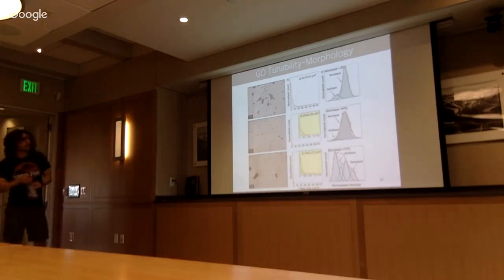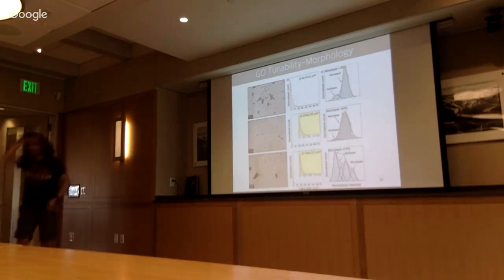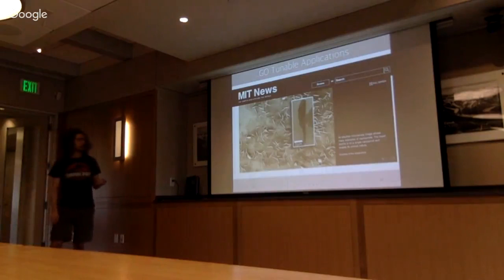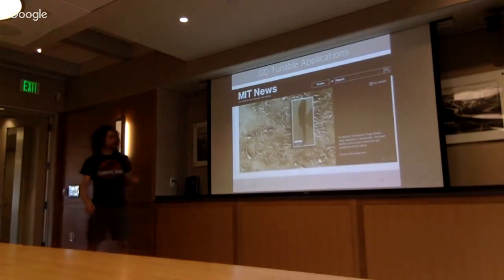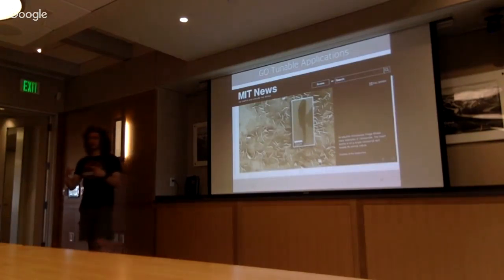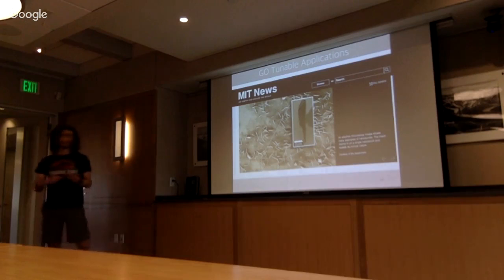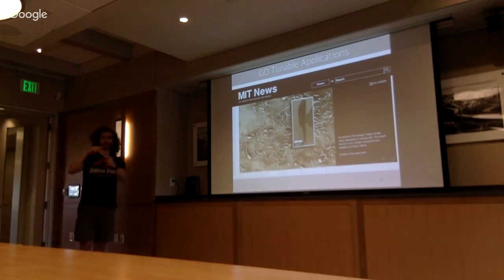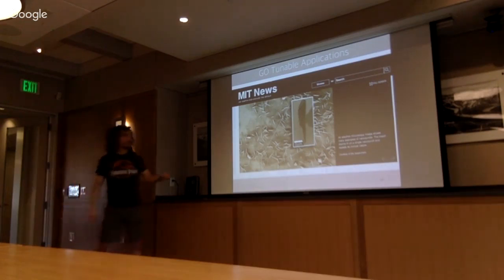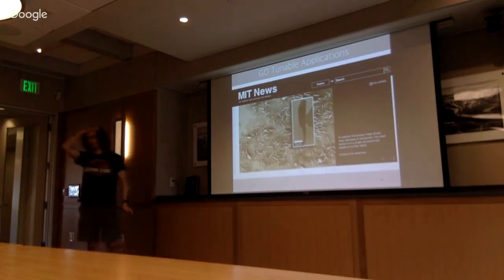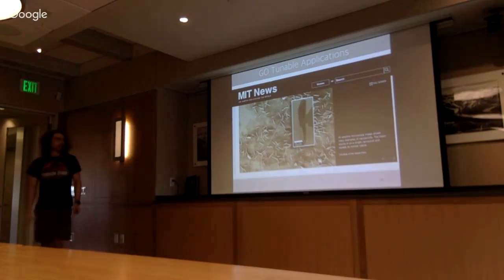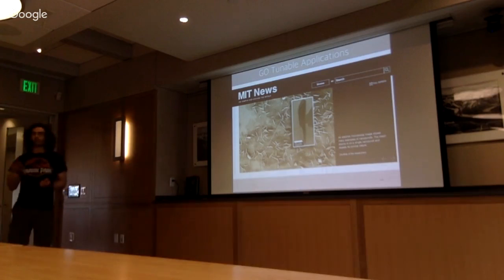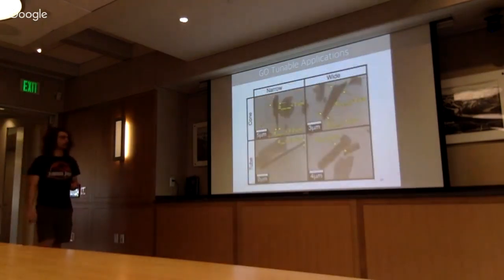So I showed you we can tune the chemistry, we can tune the morphology of this material, and this is what we did in this first paper. We took graphene oxide flakes, and then we gave some energy, enough for the flakes to scroll on themselves and form this beautiful structure. These are graphene oxide nanoscrolls. And we can modify the morphology of these flakes and the configuration.